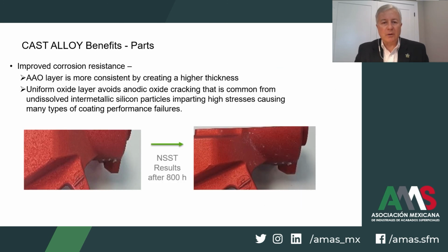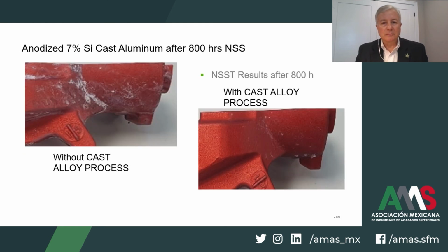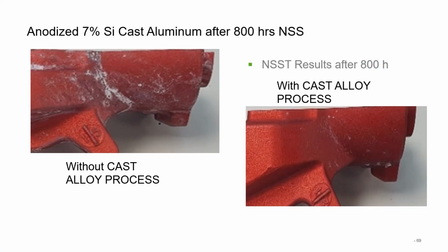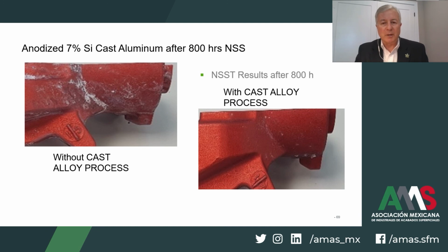The higher oxide thickness equates to improved corrosion performance, but only if the oxide is stable, uniform, and consistent, which is what the cast alloy process provides when using stage 1 and stage 2. As a result here, we realize improved resistance to neutral salt spray in lab evaluations, which corresponds to improved performance in field applications. As shown for a 7% silicon cast alloy on the right side photo using the cast alloy process stages 1 and stage 2, it has much higher performance after 800 hours of neutral salt spray compared to not using the cast alloy stages. We experience improved corrosion performance over dye-colored surfaces, generally speaking.